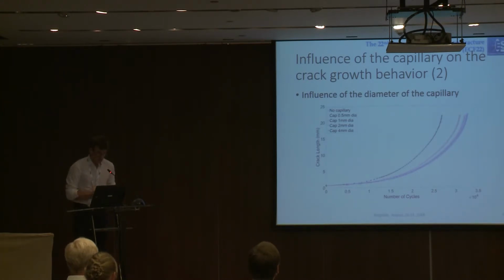What you also see is that if you work with small capillaries, so 0.5 millimeters or 1 millimeter in diameter, there is barely any influence on your crack propagation life, which is of course a good sign. If you work with much bigger capillaries, like 4 millimeters in diameter, basically it's not a capillary anymore, you have a different structure and a drastic influence on the crack propagation life. Here you have a reduction of 20%. So provided you work with small capillaries, it seems to be okay.